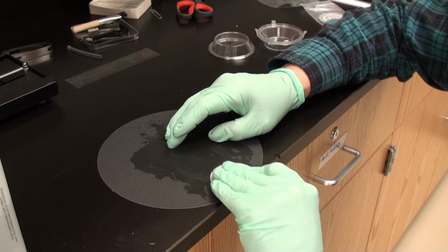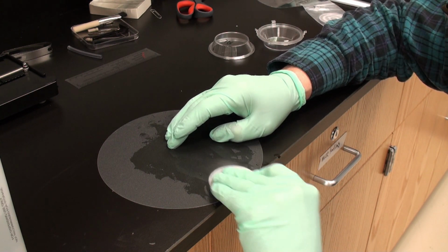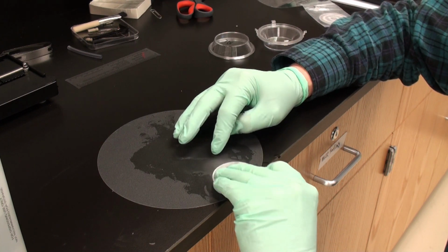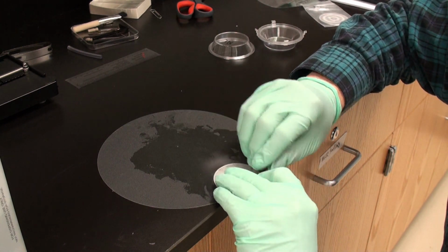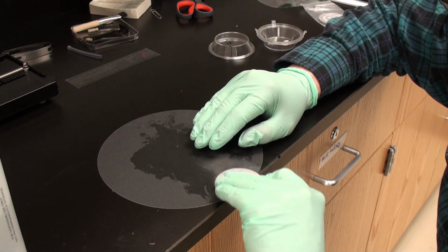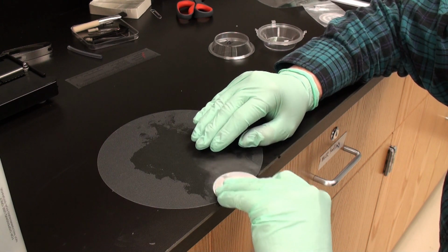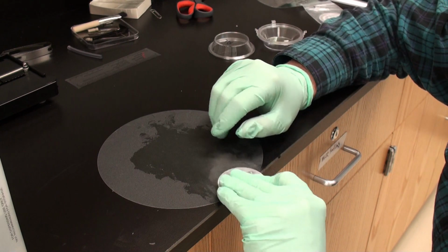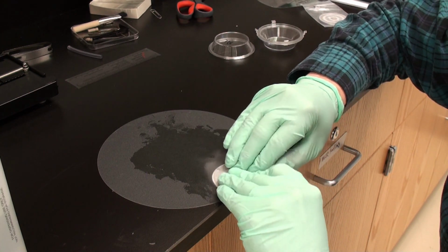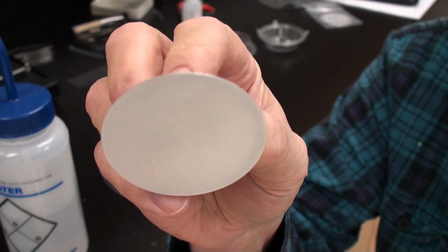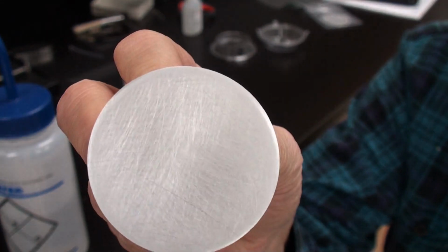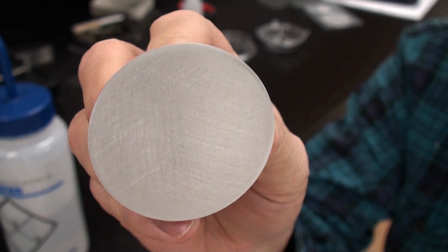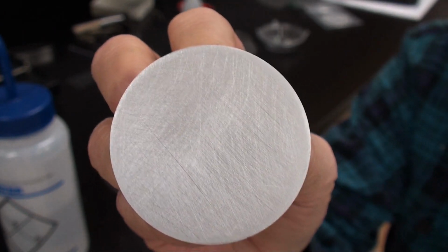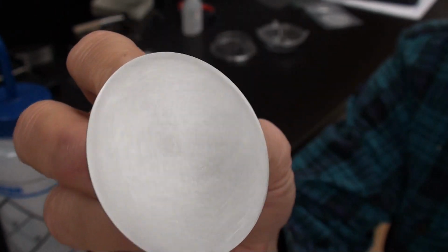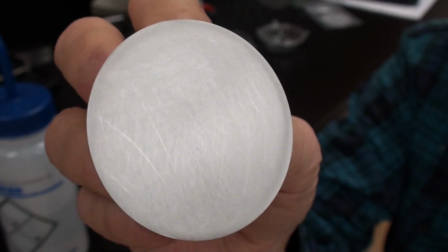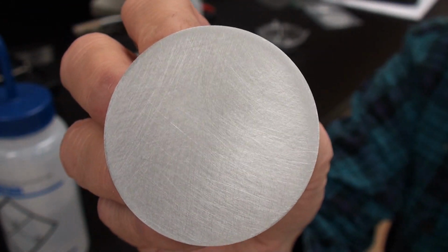So all you do is you grind them on the surface, and you can see some material is being removed, and you do this until you get through most of the oxide and you have a relatively shiny surface of aluminum to work with. All right, after a little polishing and grinding, we got a lot of the oxide off the target, and it's ready to be sonicated in some ethanol or IPA, just to make sure that we get all the little grits out of the tiny crevices and scratches we created. And then we'll mount it in the sputtering system.